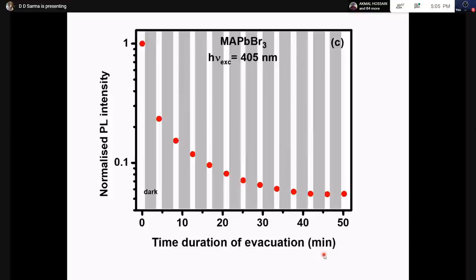And when I create an electron and hole, and remember, this electron and hole are getting created very close to the surface because this material has extraordinarily high absorbance. Remember, I celebrated the fact that it has very high absorbance, but that becomes its doom today because all the photons are getting absorbed very close to the surface. And on the surface, I have this defect state sitting, and they trap this electron and hole that have got generated. They provide lower energy states than the excitonic binding energy. And so that exciton gets split, and then they transfer themselves into these states and become dark. And then there's no photoluminescence happening.